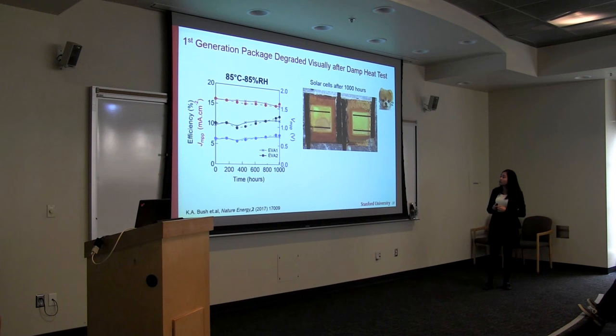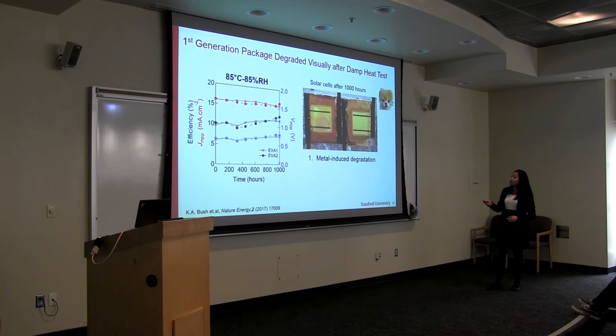However, when we look at the solar cell under the solar simulator, we see a very clear degradation. There are three things going on in this picture. First, you can see a metal-induced degradation around the conductive ribbon and the perovskite, which, if the degradation starts here, can go on and cause the other area to degrade. Second, it's a moisture-induced degradation where we think that the moisture gets in through the solar ribbon and it caused this area under the protected ITO to degrade. And the third thing is that you see some reaction between the encapsulant EVA and the perovskite under it. So in the next two slides, I will confirm whether this hypothesis that I have is true.